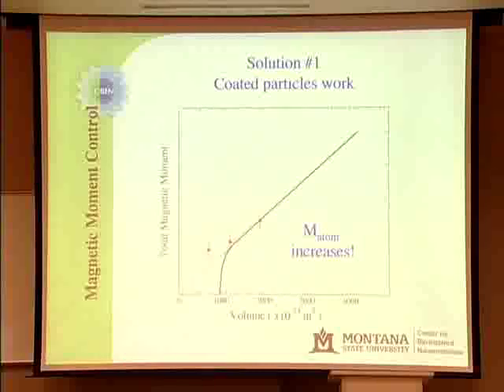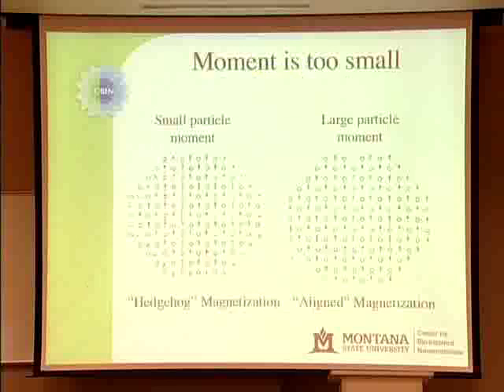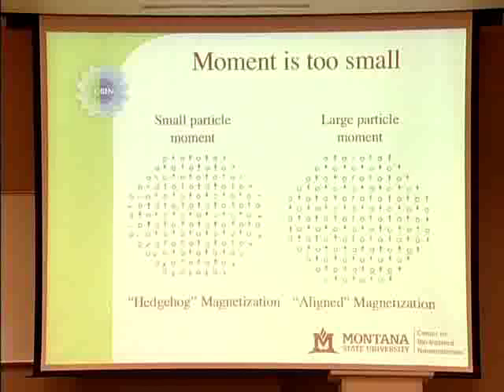And then, of course, we, being physicists and all, tried to figure out why did it do this other thing. And there's a strange effect that goes on. When I make a small particle, when the particle is big, all the moments point in one direction. When the particle is small, the surface dominates and everything wants to point out, like a hedgehog or a dandelion. Well, when the moments point outwards, I've got just as many pointing up as pointing down, as left as right, as forward as back, and they cancel each other out. And so I get a reduced moment, or zero moment. And that's what we were running up against. It was a phenomenon we didn't anticipate, magnetic surface anisotropy. And by looking at it in detail, we understood where it came from and how to get over it. So that was the little bit of work that we had contributed to understanding this magnetic phenomenon.